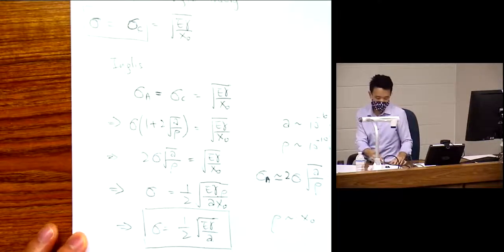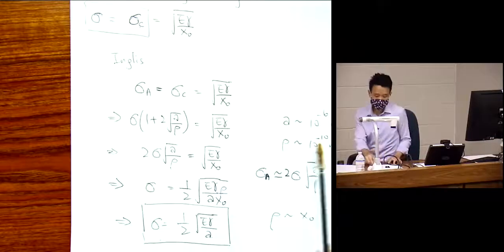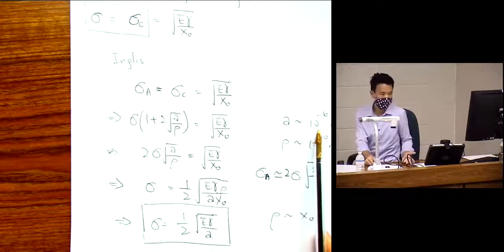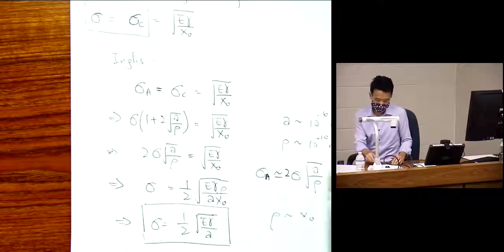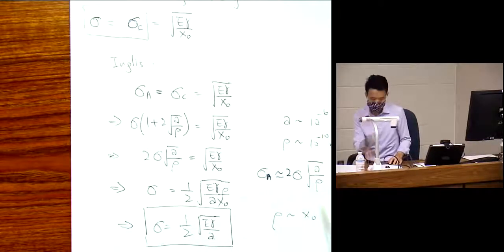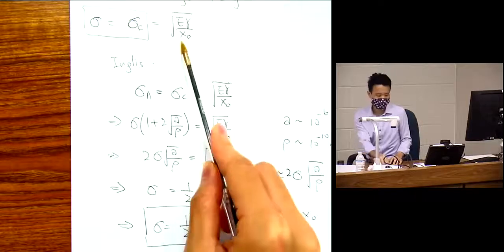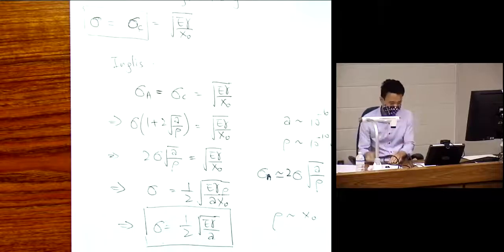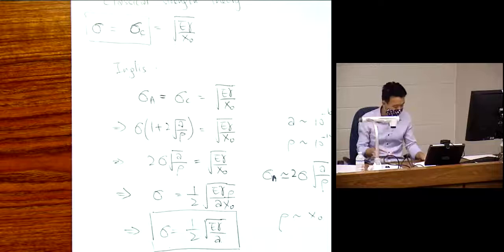And that A is typically, for ceramics, on the order of microns, which is several orders of magnitude larger than what you're going to put in here. So this is a lot closer to what you measure in reality. Now, but still, this is not extremely useful. So this is a good approximation, but